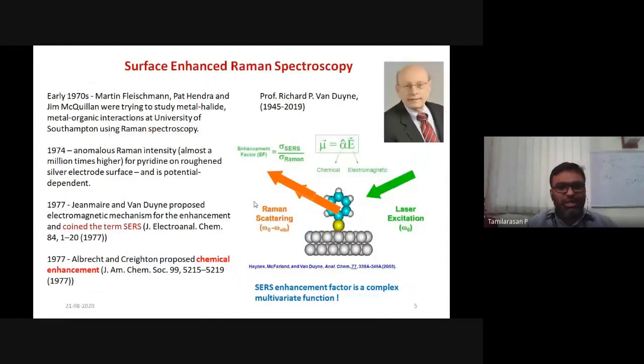And I just wanted to touch a little bit on the history of surface enhanced Raman spectroscopy. In the 1970s, at the University of Southampton, a group of scientists were studying metal-organic interactions using Raman spectroscopy. The group included Fleischmann, Professor Hendra and Professor McQuillan. And in 74, they were studying the nature of pyridine on roughened silver. They found that the Raman signal of pyridine was enhanced enormously, up to 10 power 4, 10 power 5 times. So they attributed this simply to the high surface area of silver. Because the silver is roughened, it got a high surface area and accommodated a high number of pyridine molecules.